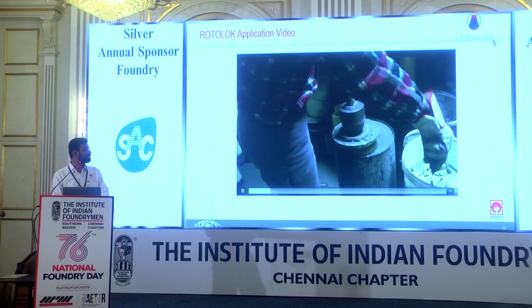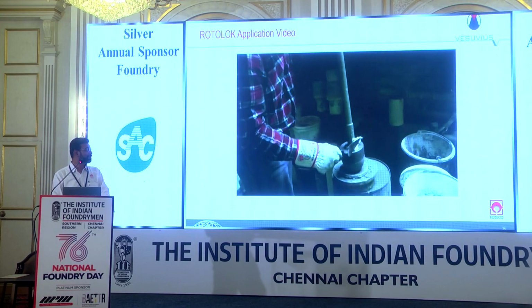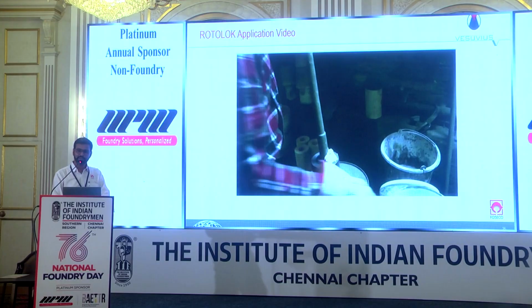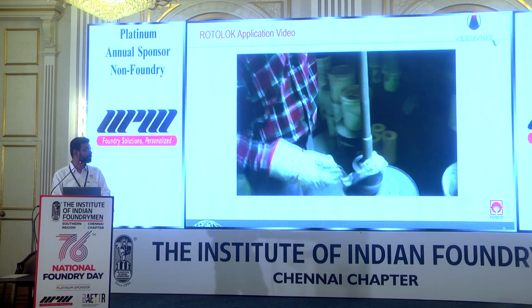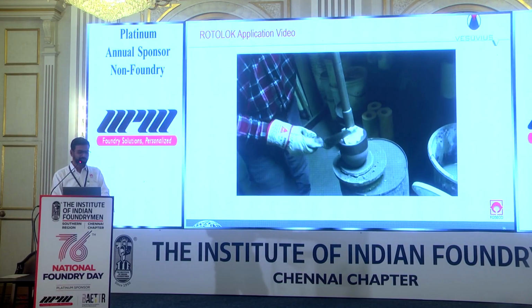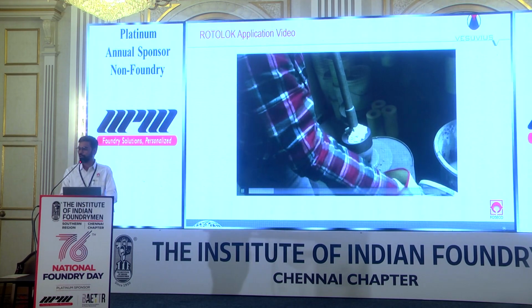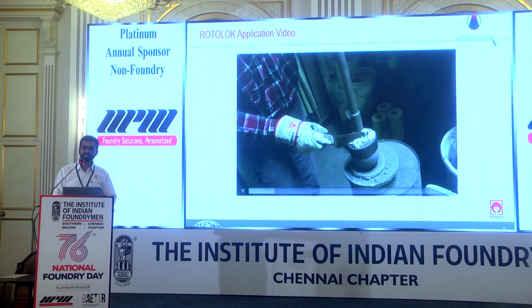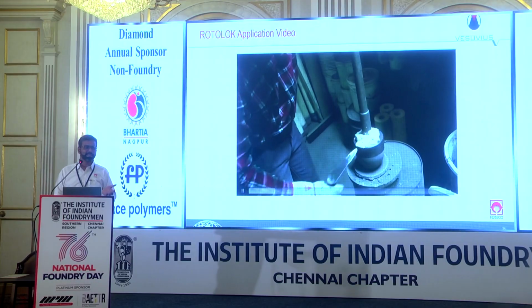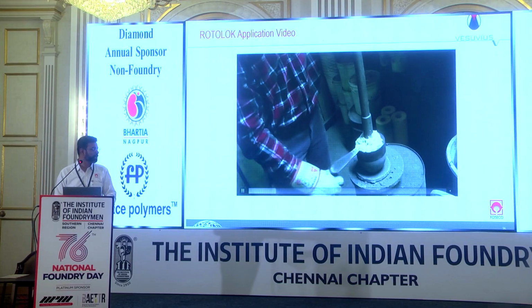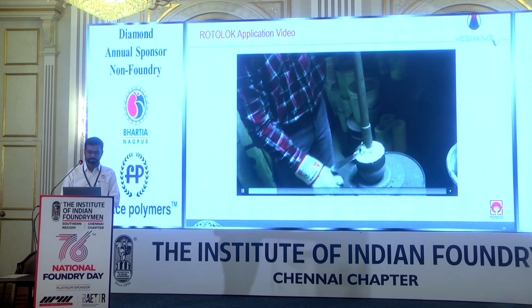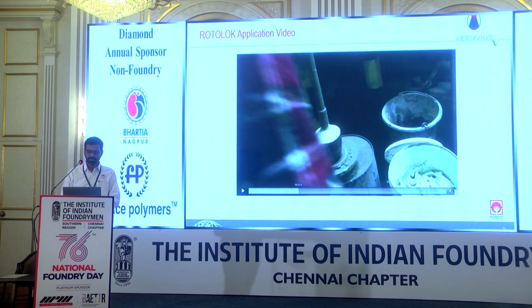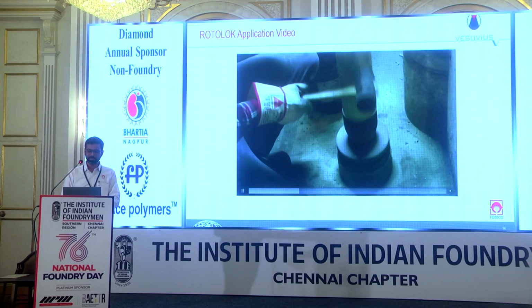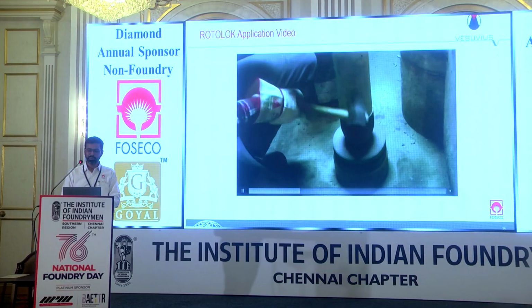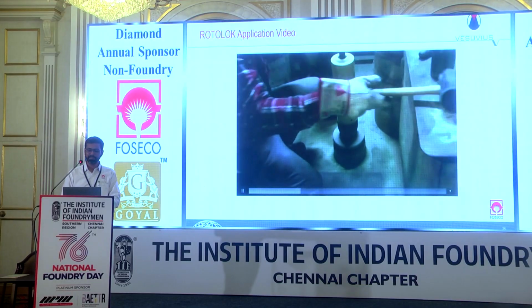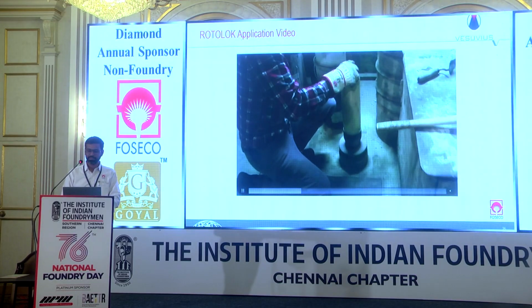So to avoid this, we have developed this product with the use of an insert, which is a ceramic insert, and this is how it will absorb the shocks which are generated during preheating and during actual pouring. We call it an assembled stopper. So the stopper head at the bottom and refractory sleeves on top of it.